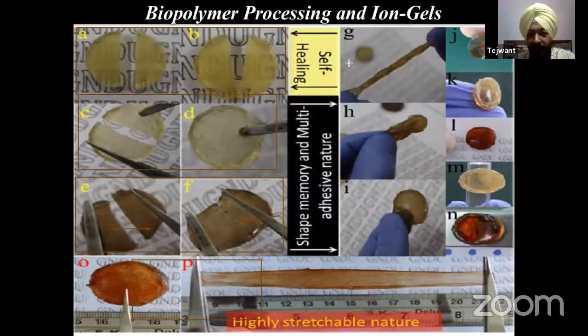Further, the gel shows a very good shape memory effect. In panel H, you can see shape memory effect means the material remembers its original shape. Whatever way you deform this gel, it adopts its original shape in a minute or 2. So that is the shape memory effect. Further, for making very good electrical connections, the electrolyte should be capable of adhering to different surfaces.